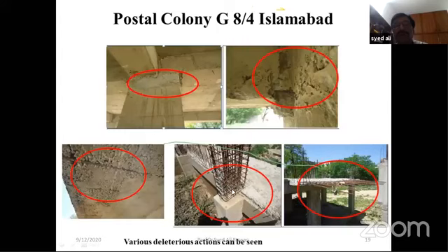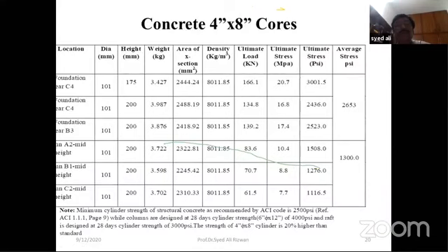You can see the column reinforcement cages, and we can measure the corrosion on that. We did this also. And then some of the portion, you can see the reinforcement of the slab, and the contractor ran away, leaving the job. So it becomes difficult to repair. So we took some 4 by 8 inches cores.